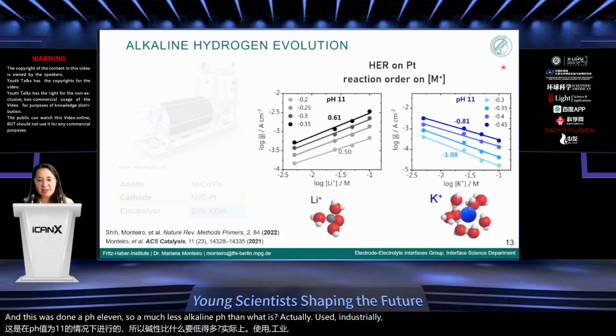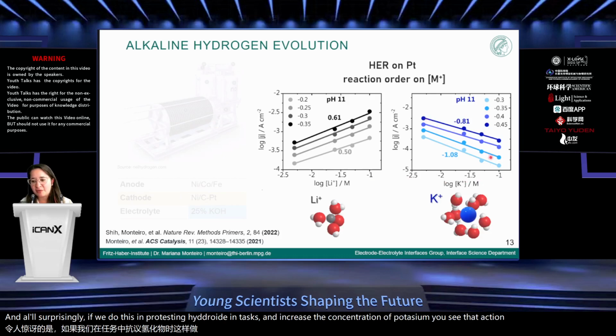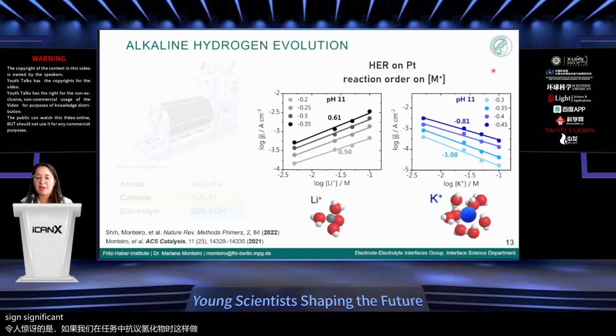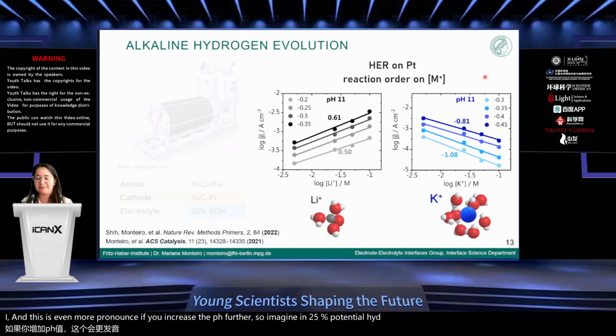And now, surprisingly, if we do this in potassium hydroxide instead and increase the concentration of potassium, you see that actually the activity goes down significantly. And this is even more pronounced if you increase the pH further. So imagine in 25% potassium hydroxide then.